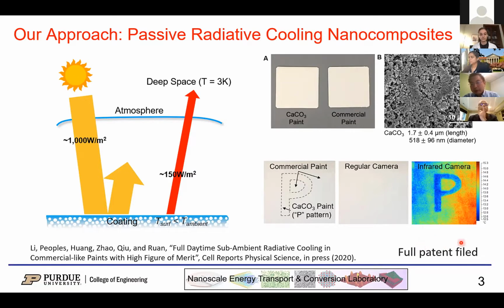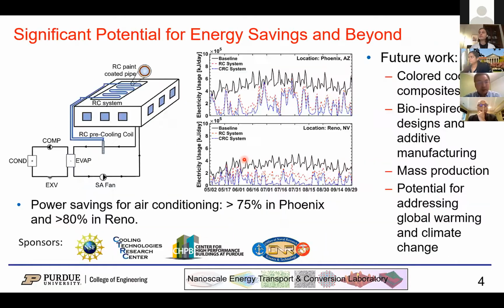We have a full patent filed already, and the article is forthcoming on this. We also did further analysis on the energy saving from using these radiative cooling paint surfaces as a pre-cooling coil for an air conditioner. We did this for Phoenix and Reno. The baseline is without our system, and then we compare our two radiative cooling systems. We can save power for air conditioning by more than 75% in Phoenix and more than 80% in Reno.